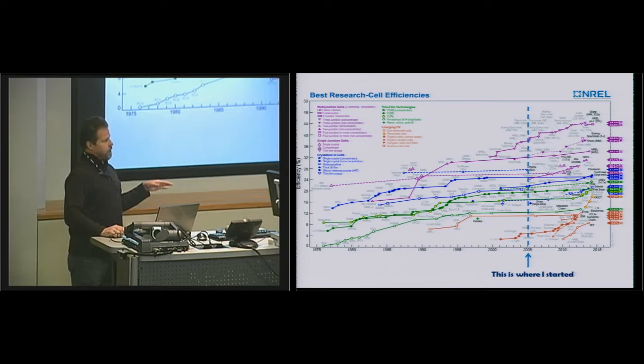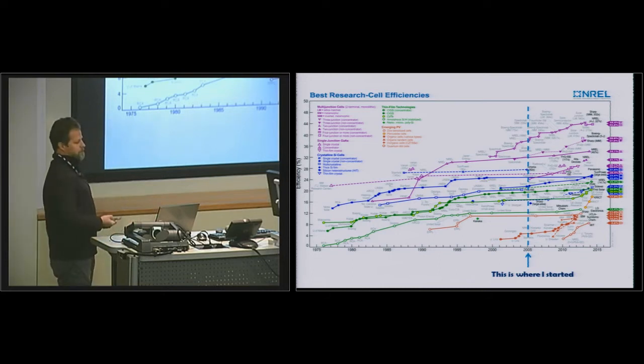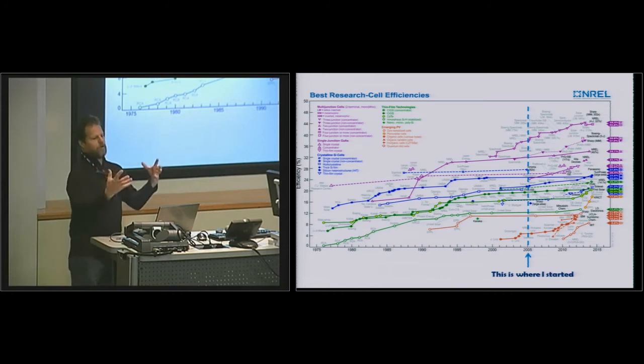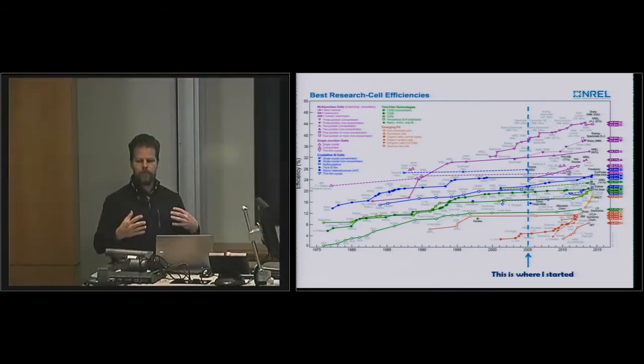CIGS, on the other hand, was relatively stable. It was a stable material, had a higher record efficiency than cadmium telluride. It's a direct bandgap semiconductor. And I'm a nanomaterials chemist, and so I was also interested in it because nobody had made nanocrystals of copper indium gallium selenide. The way we do our chemistry is we have a beaker of solvent, and we throw in some reactants to make a material. So if you want to make a quaternary compound of copper, indium, gallium selenide, you have to put four elements into this flask, and those things can react in multiple ways. You can get multiple different phases, and so it's not obvious you can actually make this material.